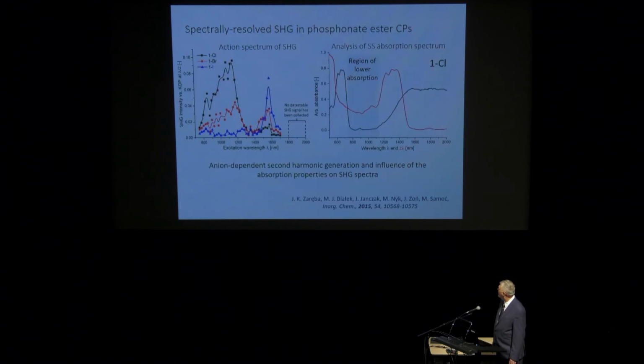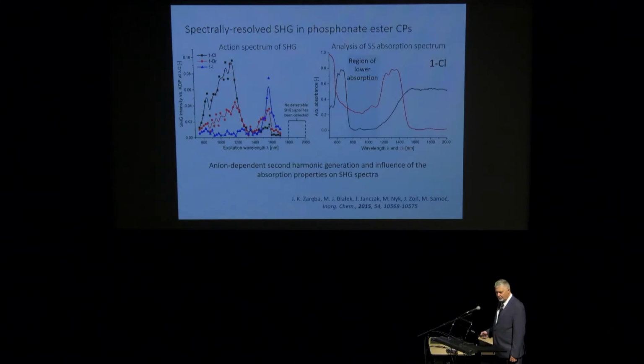We have to be careful there, because in materials like metal organic frameworks, you usually have lots and lots of different transitions, different excited states. So one has to find areas in the spectrum where this generation of these harmonics is not hampered by the presence of absorption. So this is an example where we have a series of 3 MOFs containing Cl, Br, and I. And in one range of spectra, you see this iodine containing is the weakest, and another region, it is the strongest. So one has to be very, very careful when analyzing and interpreting powder measurements in nonlinear optics.